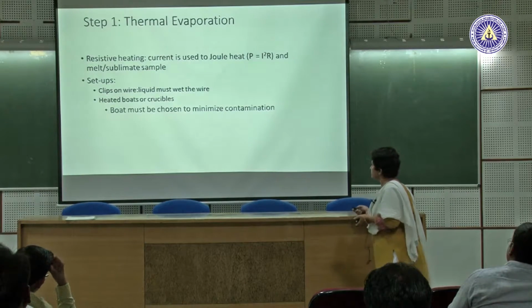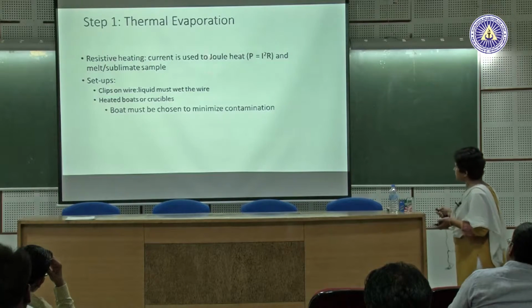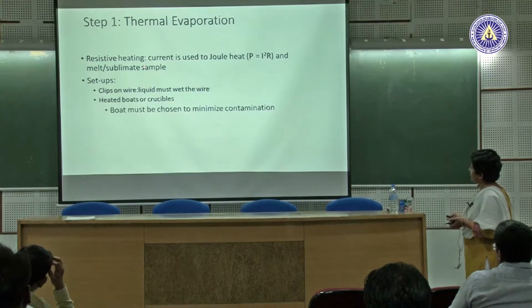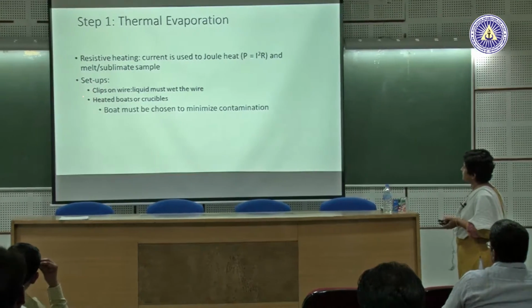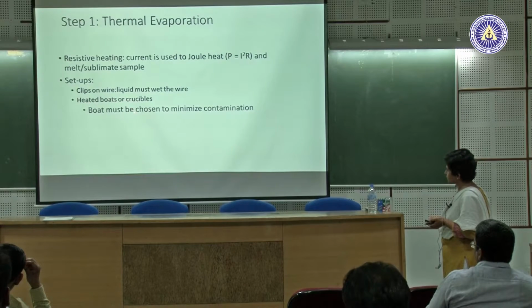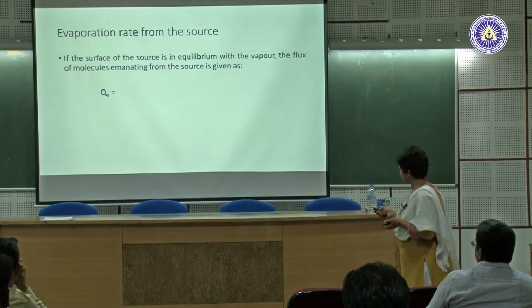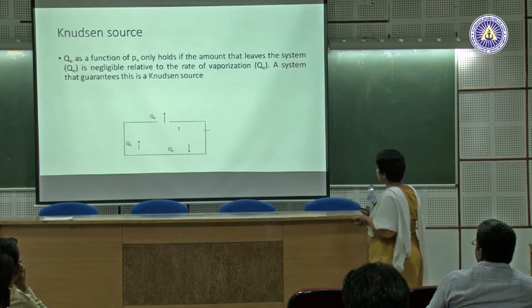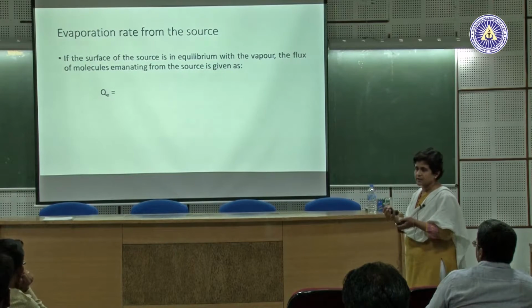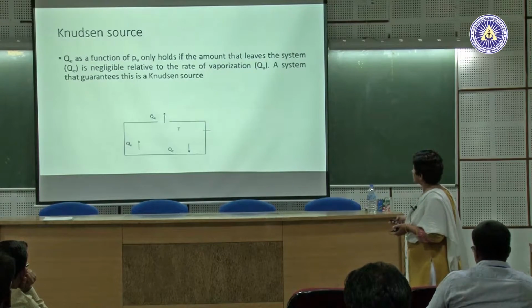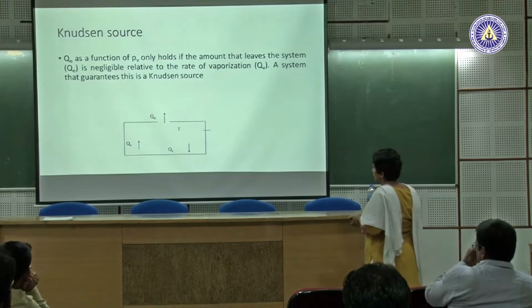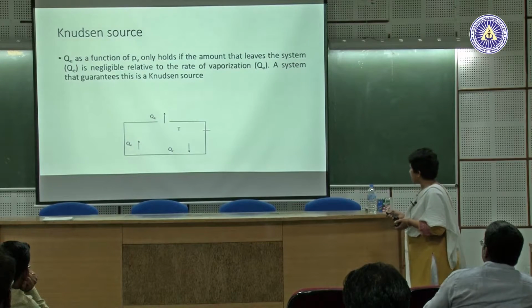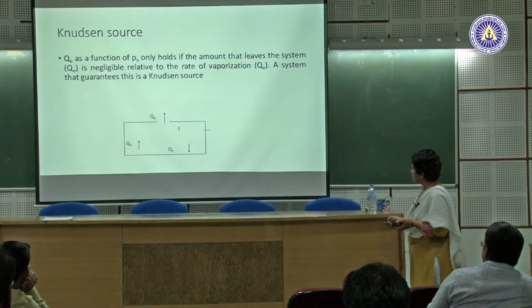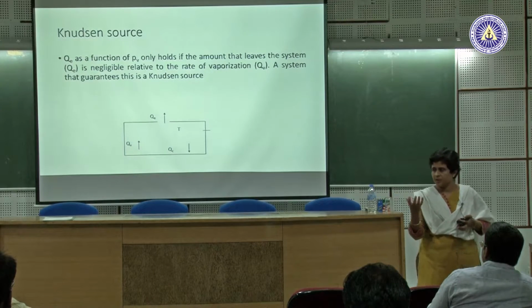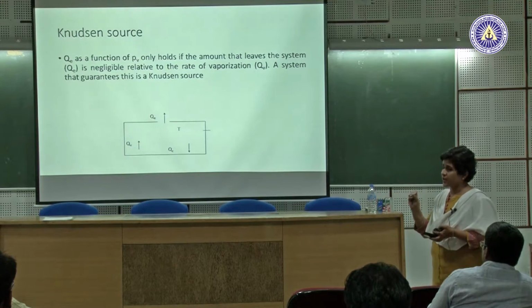For thermal evaporation, you basically use resistive heating. Current is used to get the heat using Joule heating, and the material is melted or sublimated. It can be done using clips on wires or boats. I have some example to show how it works. The equation somehow got dropped. You can also calculate, using gas kinetic theories, what flux you will get from a particular source. You can even design something called a Knudsen source, where you put the material in a closed container with only a very small opening, to give a thermal equilibrium situation if you want to control the evaporation rate very, very well.